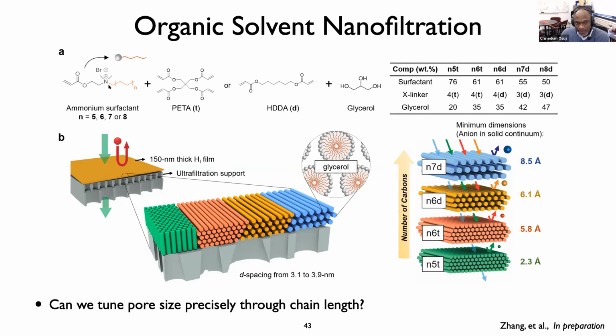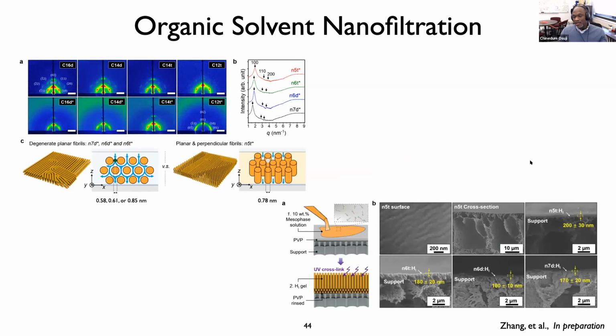He looked at a series of different surfactants with differing chain lengths and a few differing cross-linker chemistries, and in so doing, produced membranes with a small but precise and steady variation in the expected transport regulating feature size, and looked at the resulting changes in the rejection properties of these membranes.